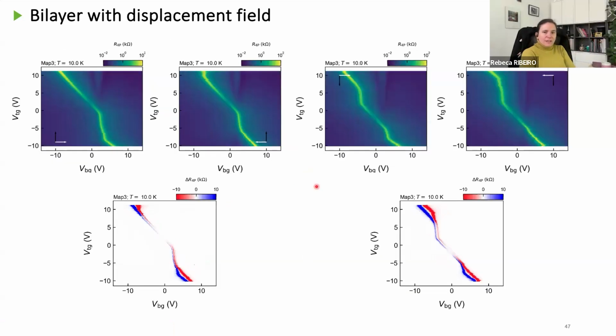So for the moment, we have a strong hysteretic ferroelectric behavior started by the crystallographic alignment that we control with our AFM. We also found something quite interesting, and for full disclosure, this ferroelectric effect has already been reported by 3 groups in the world. It has been mostly reported in fixed angle devices. They do not know how to reproduce it, and they always associate this with the formation of the moiré superlattice.